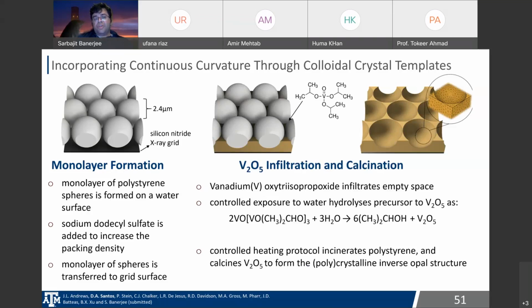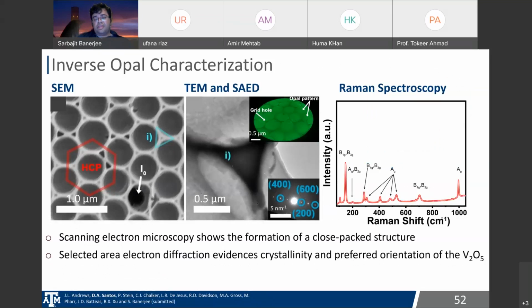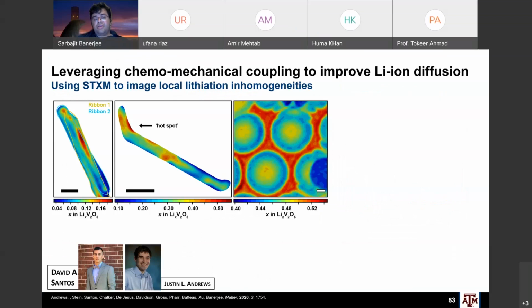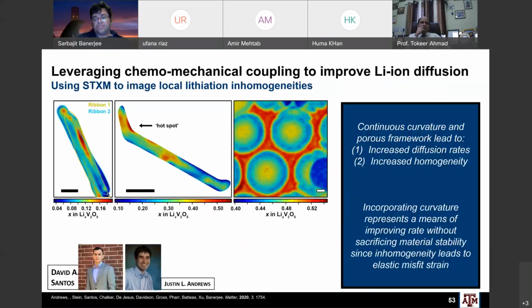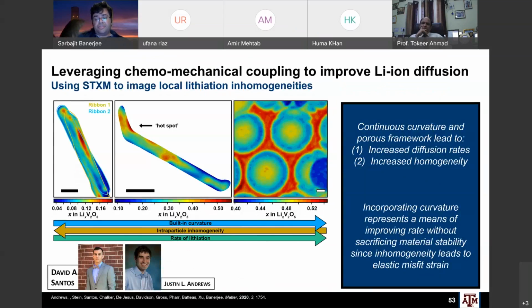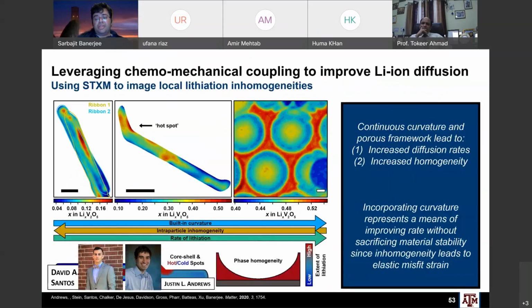So we can form these V2O5 structures, these inverse opals. This is we templated using polystyrene spheres, and then you can see here individual particles give you large hotspots, but you generally end up getting very homogeneous lithiation inside these inverse opal structures, right? So incorporating curvature represents a means of improving rate without sacrificing material stability, since inhomogeneity leads to elastic strain. As long as you can get this very homogeneous lithiation to take place, you no longer have these hot spots and cold spots, and you can get very homogeneous lithiation.